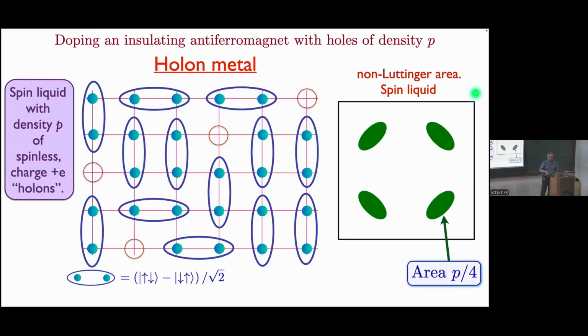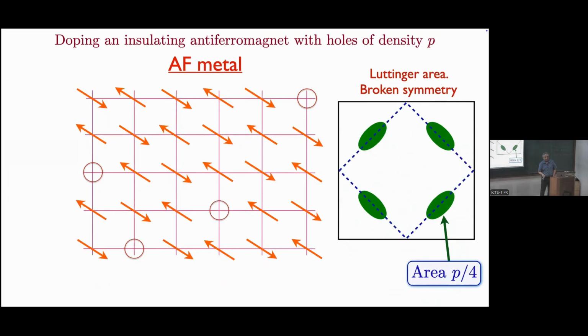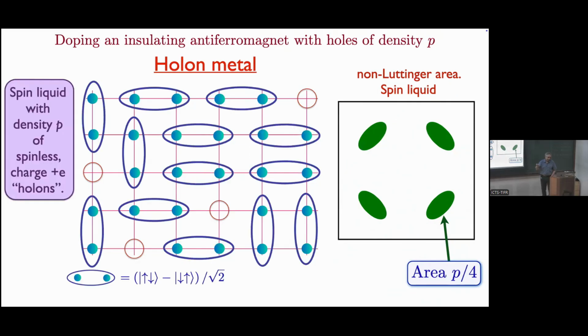And what's the area? Well, here, there is no magnetic Brillouin zone. There's no broken symmetry. But these are spinless. So now there are 4 valleys, if you had 4 pockets, and in many models you do. They're not necessarily at some geometric point, halfway between here and there. They could be at any point. But they're spinless, so there's no degeneracy for spin. There's a factor of 4 for valley, so that gives you area P over 4, which is the same as the spin density wave state, somewhat unfortunately. But anyway, this measurement can't distinguish between this state and this state. Other measurements could, but this one, magnetotransport, can't.